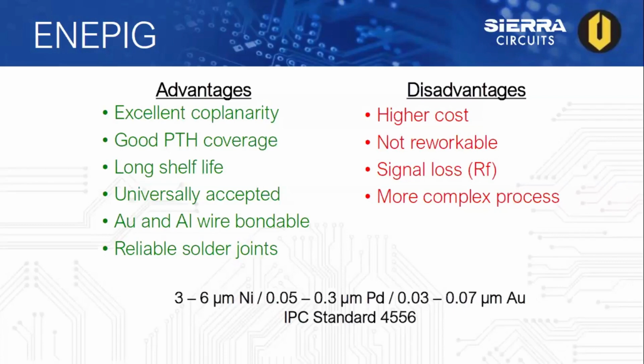ENEPIG is governed by IPC 4556, which is the ENEPIG plating for PCBs. Similar to the ENIG review we discussed earlier, the IPC committee came up with this specification to ensure high reliability for the PCBs, and the thicknesses, as you can see for the nickel, are very similar with 3 to 6 microns. However, with palladium, you go from 0.05 to 0.3 microns, and gold from 0.03 to 0.07 microns.